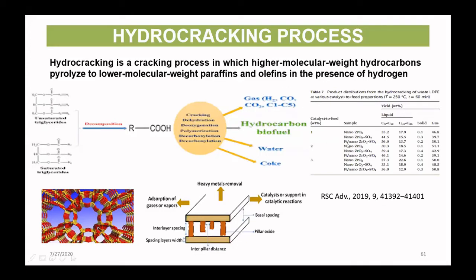We use zirconia and sulfated zirconia, with platinum as the active material supported on the sulfated zirconia, and we can see the distribution of the product. The result is some in the gasoline fraction, and some, I think this is the diesel fraction.